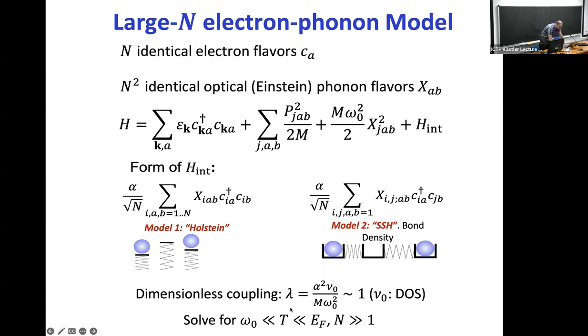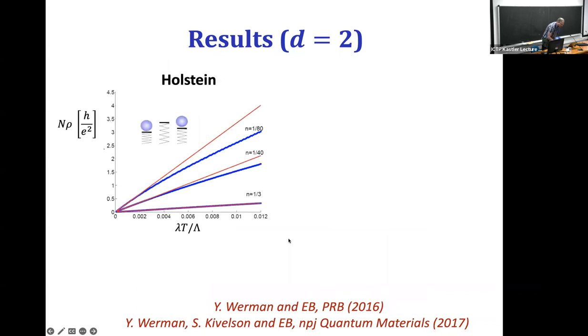And we're interested in this context in the regime where the temperature is much bigger than the Debye frequency, but much smaller than the Fermi energy. And it turns out that these two models actually give a very different behavior in this case. In the Holstein type model, resistivity grows linearly with temperature. And when you reach the Mott-Ioffe-Regel limit, where the mean free path of the electrons becomes order one, there's a kink in this slope, but it just continues linearly with a different slope.